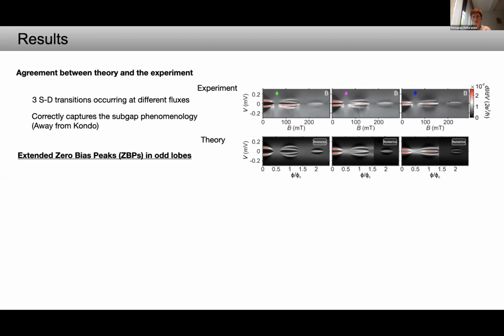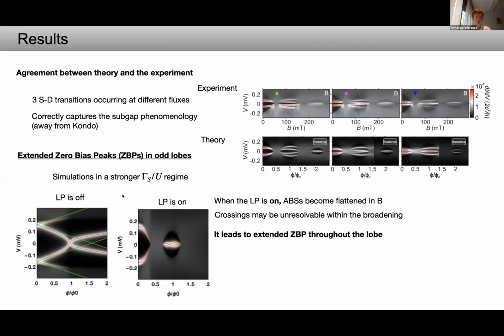So the last panel is interesting because it shows an extended zero bias peak in an odd lobe. To get a better understanding of this behavior, we plot 2 more dI/dV simulations with the pole structure superimposed in red in a different coupling regime with larger gamma S. On the left, the Little-Parks effect is off. It means that the gap is constant. And in green, we plot the expected behavior for a purely Zeeman-driven regime.